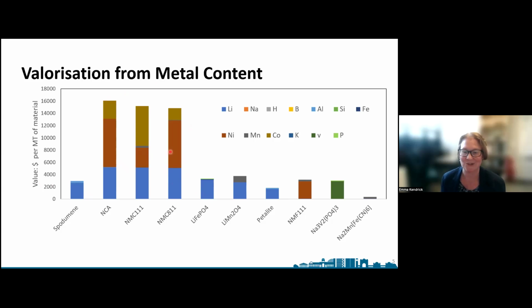So cobalt and nickel have a very high value. And so it is economically viable to recover some of these high value materials. If we move, however, to lithium iron phosphate, as you can see, we're competing with the primary ores, but moving to some of the sodium systems, actually the value can be quite low. And we do need to consider how we do this recycling to retain some value rather than it being just the metallic value from the composition of our cathodes in these materials.